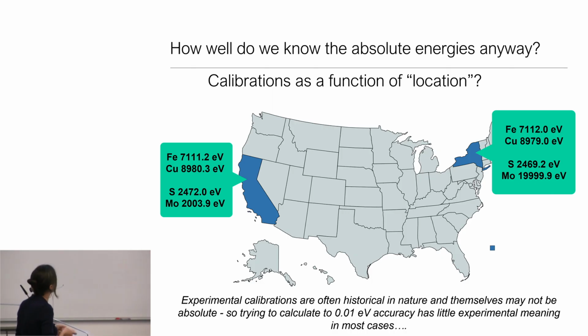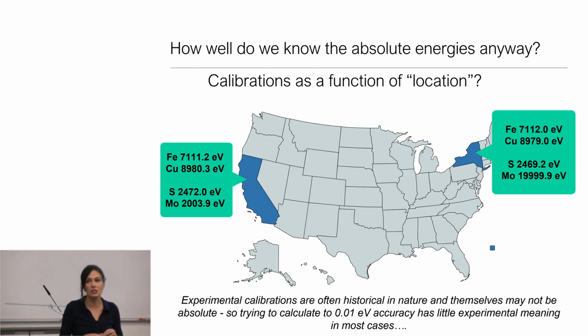And it gets even worse for other metals. You can see here the differences in copper. Sulfur, even at low energy, these shifts are more than 2 electron volts, right? And so again, so much of this is historical. And so when theoreticians tell me they want to really accurately get the energies, one has to ask, do the experimentalists actually accurately know them? And this is why we have to thank people at the NIST and the PTB who are pushing the forefront of actually getting these numbers right, but don't pretend that we as X-ray spectroscopists know these numbers for many of the things that we're measuring in an absolute sense, okay?